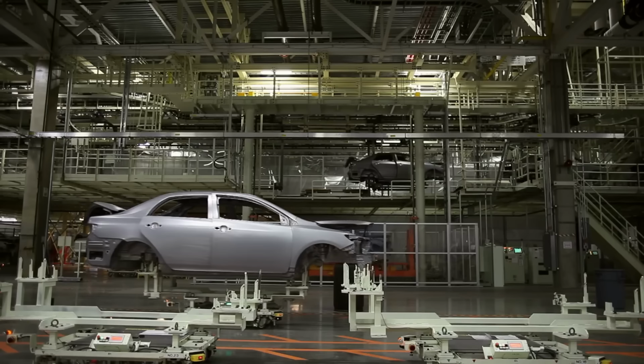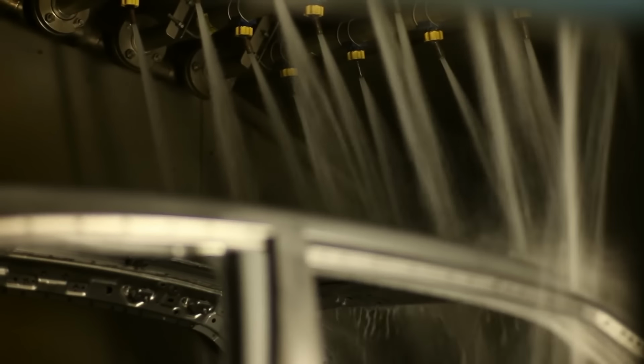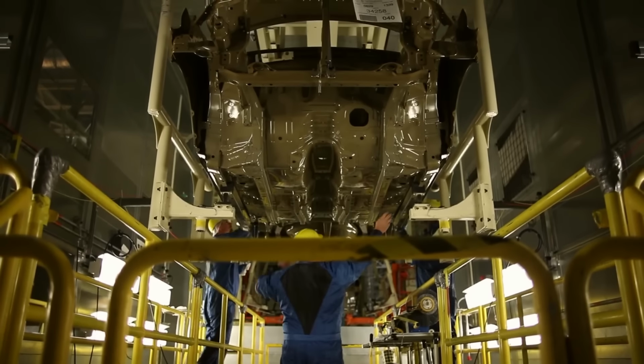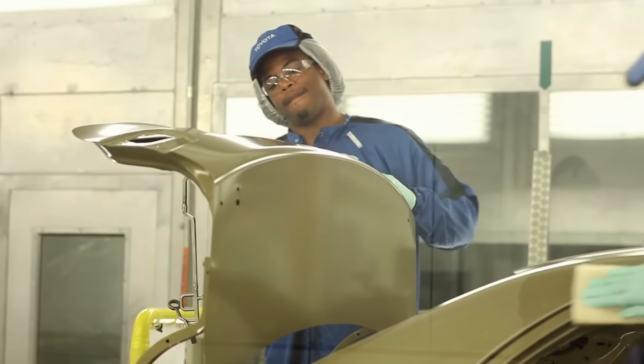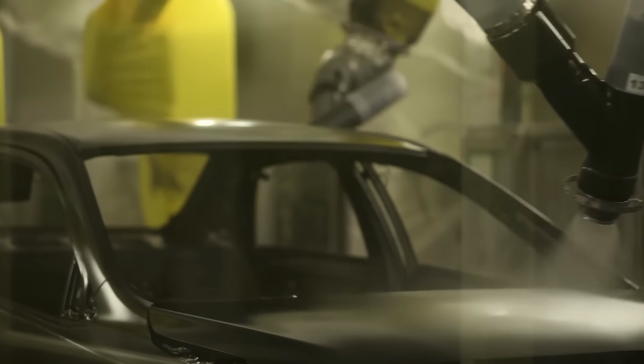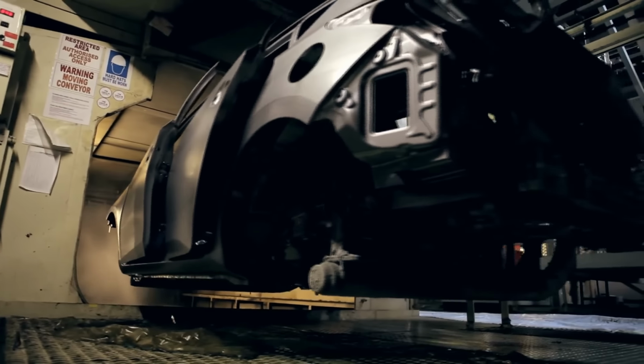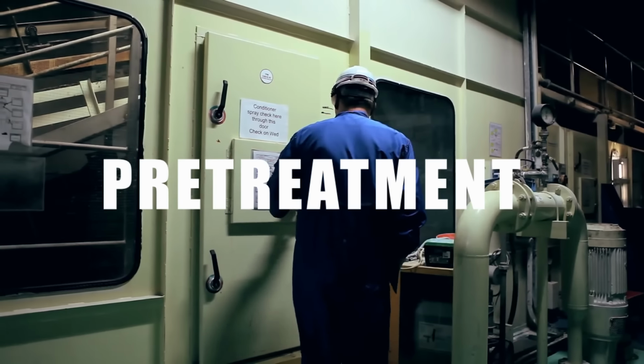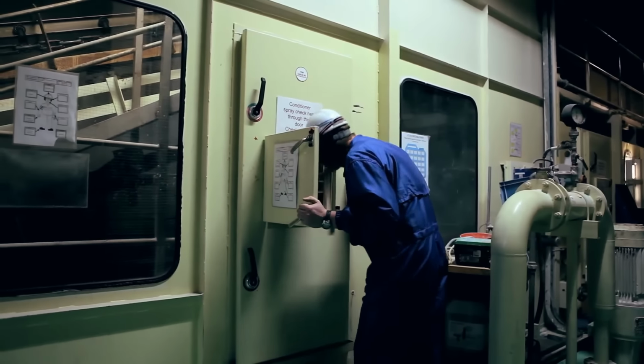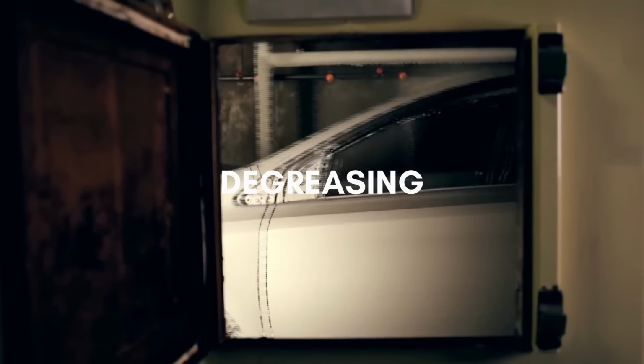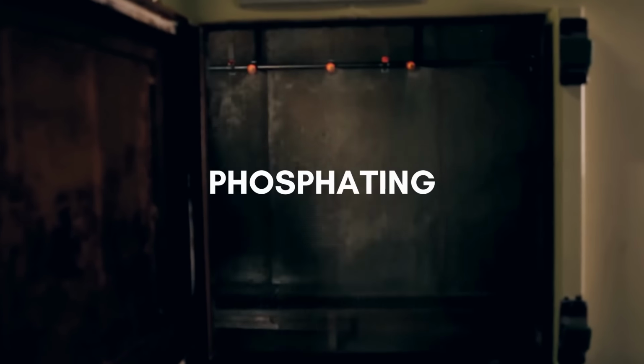By the turn of the century, modern automotive coating methods have brought complete finish application time down to as little as 12 hours on high-volume assembly lines. In general, this highly automated process occurs in 5 steps. In the first step, called pre-treatment, the freshly welded vehicle body goes through 3 primary liquid dip processes of degreasing, conditioning, and phosphating. These cleaning baths remove contaminants from the welding process, as well as help the primer to bond onto the metal.